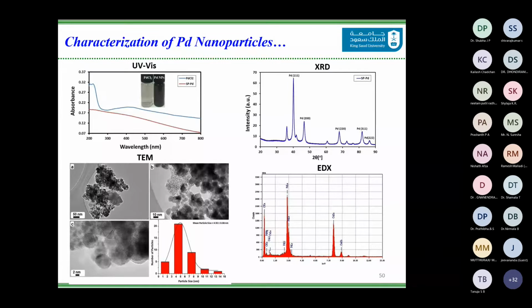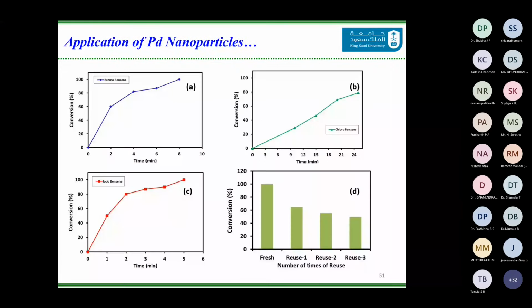The TEM microanalysis revealed that the particle size is between 10 to 20 nanometers in this case, and they are very fine, minute particles around. But at around 4 to 5, you have the major chunk of nanoparticles. The EDAX has confirmed the presence of palladium salts, and we used this for Suzuki coupling. In the previous study, we just used bromobenzene as the precursor. However, in this case, we used bromo, iodo, and chlorobenzene. And we have seen that iodobenzene reacts the fastest, and we get a product within 5 minutes of reaction time, whereas bromobenzene, we get 100% conversion in 8 minutes, while chlorobenzene gives us about 80% of the product after 24 minutes.